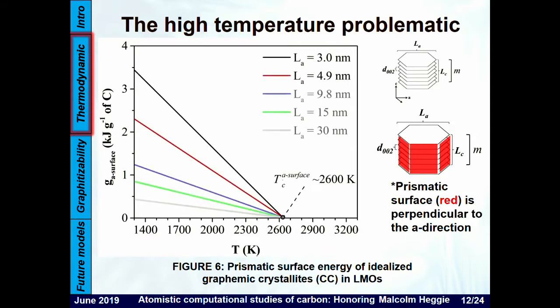Unfortunately, there's a problem with this model, and this is the problem that my PhD focused on. If you convert the Gibbs energy equation into a surface energy model for this prismatic surface, which is in red in the figure, what you obtain is that there is a fixed temperature where the surface energy reaches 0, at about 2600 Kelvin. This problem was hard to interpret, and at the end of my PhD, what I realized is that it was related to the graphitization of carbon materials inside LMOs, which yielded a second model, which I will present in the following slide.